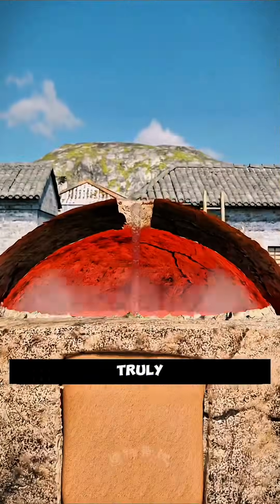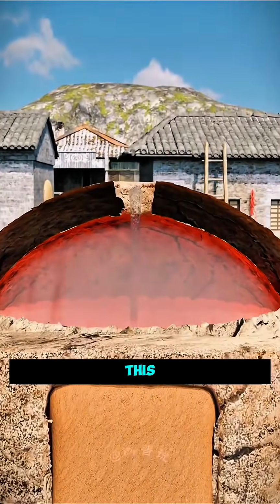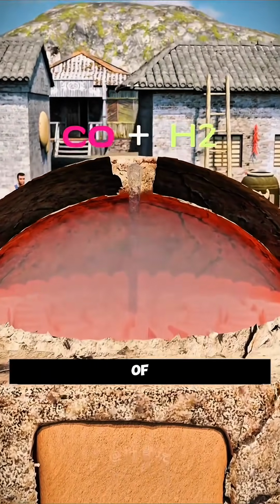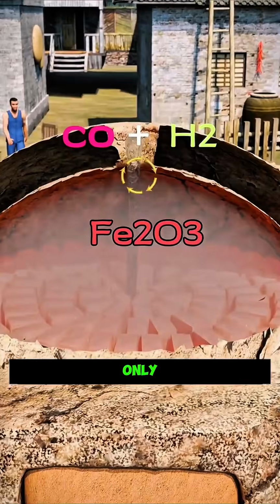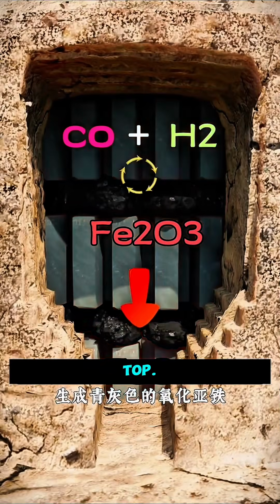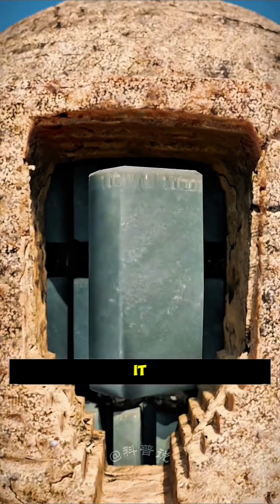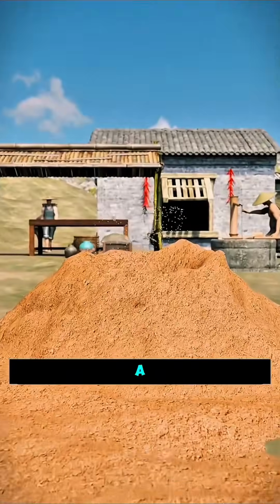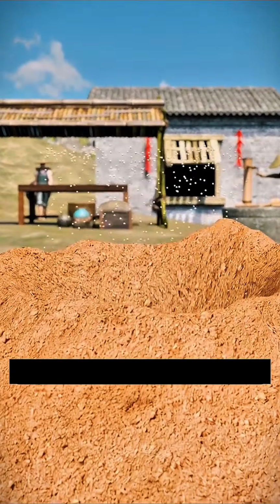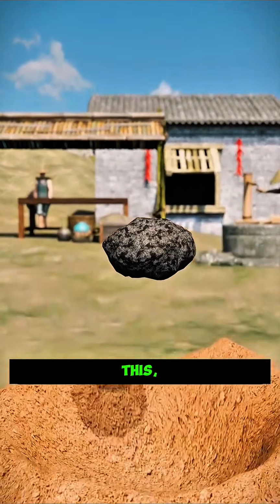But if you truly wanted to make the strongest brick, this is where the game changed. All the openings of the kiln were sealed, leaving only a small hole at the top. Water was then poured into it slowly. Inside the kiln, a chemical reaction transformed the red brick into a much stronger deep blue-gray brick. If you think nothing could be better than this, the biggest secret is still to come.